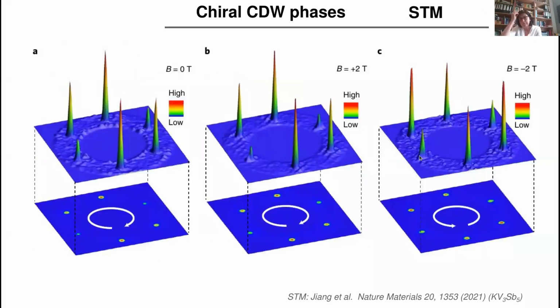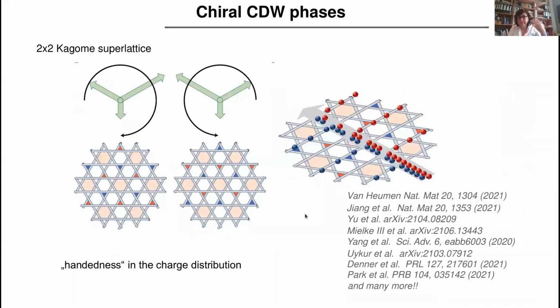Moreover, this group observed the following: if you apply a magnetic field in the charge density wave phase, the amplitude of these charge density wave peaks changes by changing the direction of the magnetic field. It was interpreted as a breaking of time reversal symmetry on application of the magnetic field, and this has induced a burst of different experiments trying to analyze whether this chiral charge density wave phase exists.